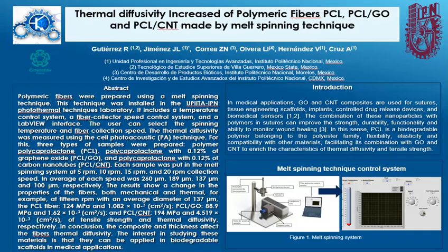Abstract. Polymeric fibers were prepared using a melt spinning technique. This technique was installed in the UPITA IPN Photothermal Techniques Laboratory. It includes a temperature control system, a fiber collector speed control system, and a LabVIEW interface. The user can select the spin temperature and fiber collection speed. The thermal diffusivity was measured using the photoacoustic technique.